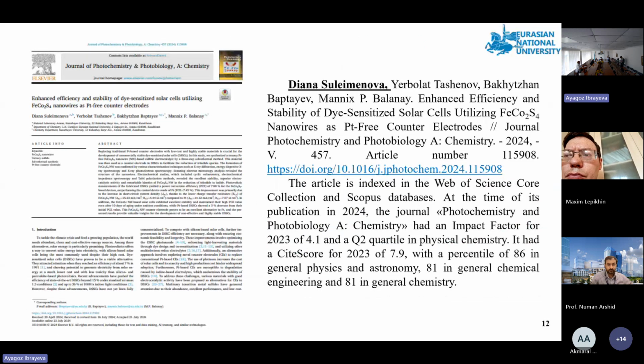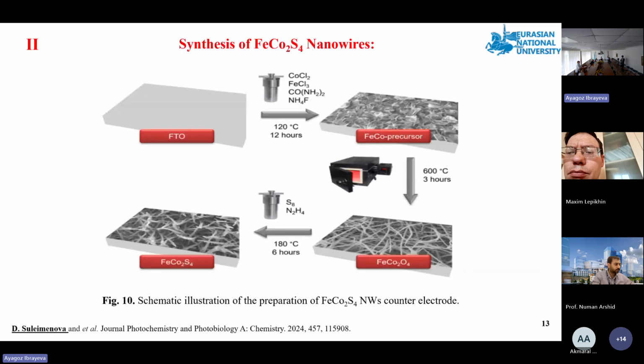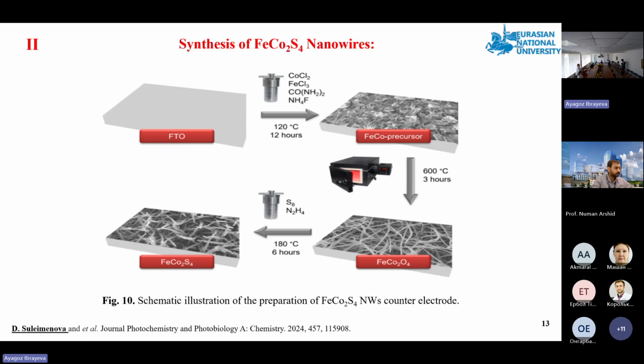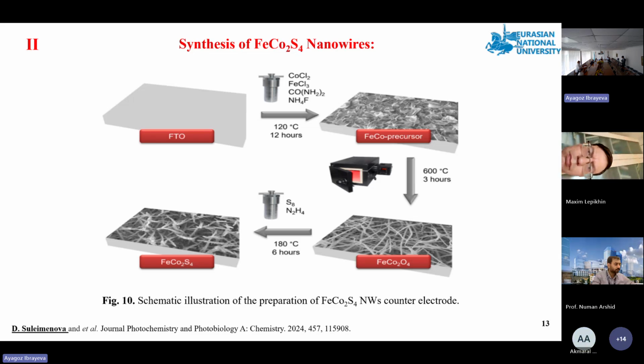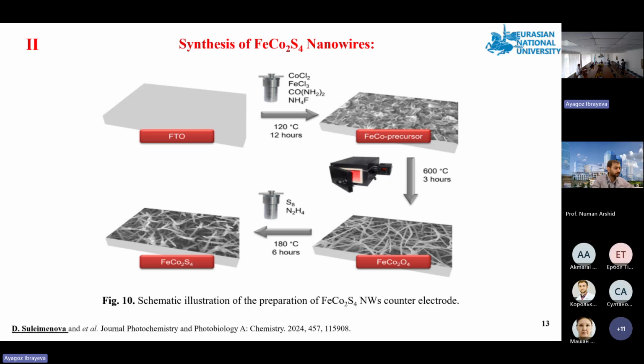According to the second provision, we published a research article in the journal Photochemistry and Photobiology A: Chemistry. Synthesis of ferrum cobalt 2 S4 nanowires was obtained in 3 steps. First, we take the ferrum cobalt precursor, then we anneal the precursor and obtain ferrum cobalt oxide, and then the third step is the sulfurization process. We obtain ferrum cobalt 2 S4 nanowires.